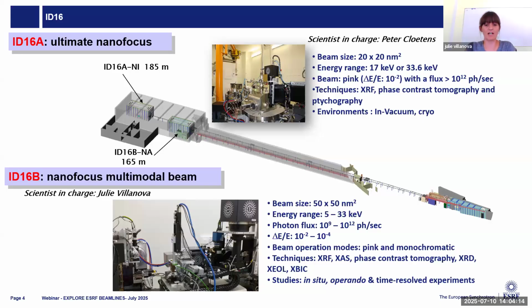We have an experimental hutch that is at 165 meters from the source. Our source is an insertion device. Then in this experimental hutch, we focus our beam to 50 by 50 nanometers, thanks to 2 sets of KB mirrors. We have a grazing incidence fixed curvature one to work from 6 to 14 keV, and a multilayer to work in a Bragg condition, to work from 17 to 33 keV. Thanks also to the different optics we have upstream in the optical hutch, we can work either in monochromatic beam or in pink beam.